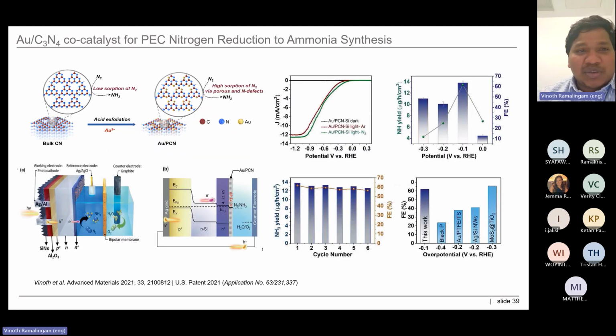So this is another project where we used a gold-coupled graphitic carbon nitride as co-catalyst, but this is not for hydrogen production. This is for nitrogen reduction to ammonia synthesis. What I'm trying to say here is, while choosing the catalyst material that can help you do various kinds of reactions, we use the same photocathode device, but when we change these catalysts, they can change the reactions. For example, here, nitrogen to ammonia synthesis, and we got this work published in 2021, which showed really good nitrogen to ammonia performance.